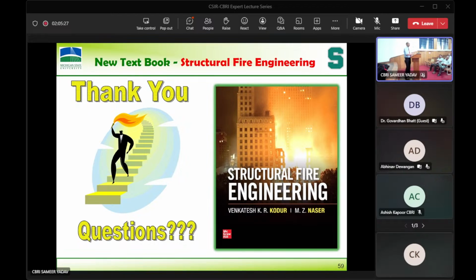Whatever common sense tells you is a lot of times not right. Sustainability is not good for fire. Sorry to say that. I know, unfortunate, because you are reducing your cross section. These days, you have very thin sections. We are making holes everywhere. Hollow core slabs. And our bridge girders used to be very nice. Now everyone wants to use modern shapes, unfortunately, including our structures. It's very bad for fire because thermal mass is the one which used to give us good fire resistance. That's going away. We never gave importance to tensile strength.